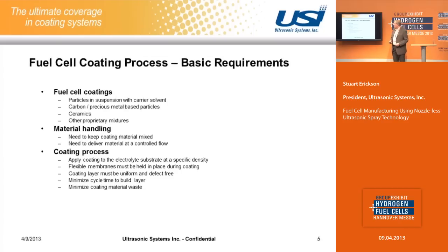Fuel cell coatings are essentially a material, a carrier solvent with particles that are in suspension. These can be ceramic particles, they can also be precious metal, carbon-based particles, or other proprietary materials. In order to handle these materials, you have to keep the material mixed because suspension materials tend to fall out of suspension fairly quickly. So you need to have a mechanism to keep the material mixed for the coating process, as well as to be able to deliver the liquid to the spray device in a controlled way.